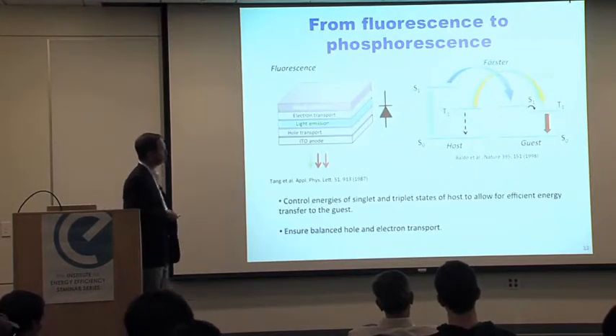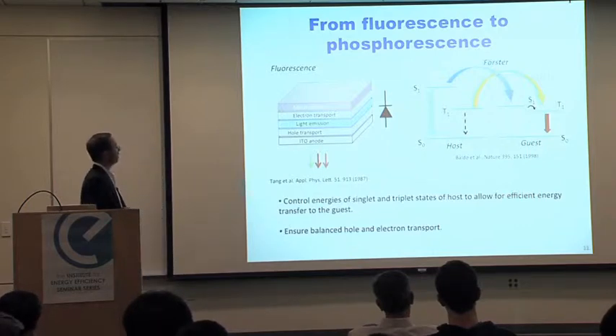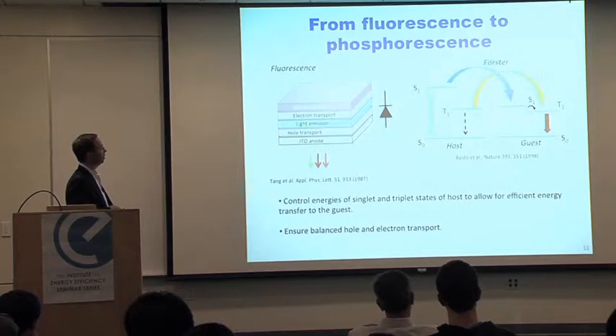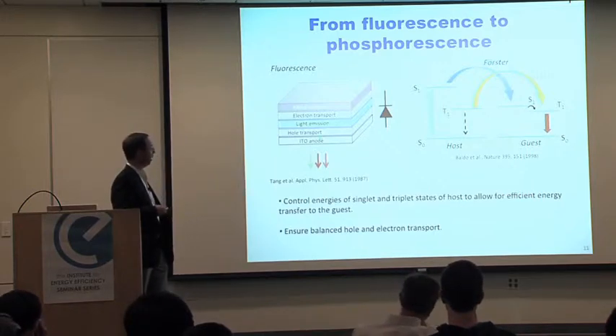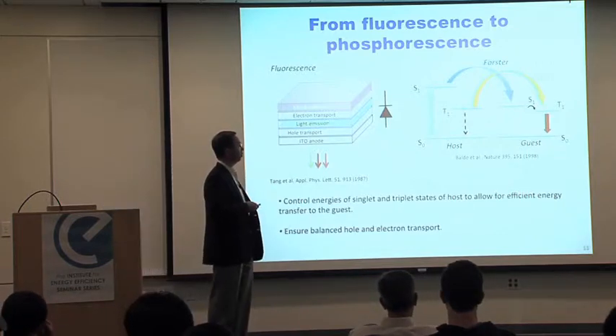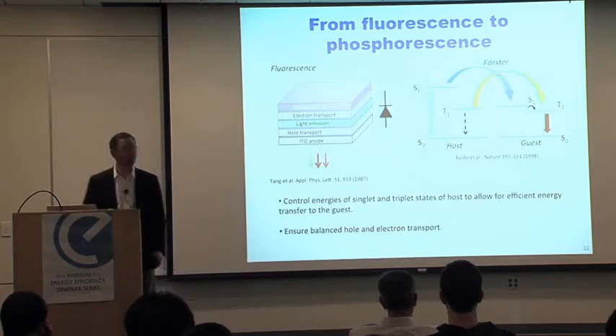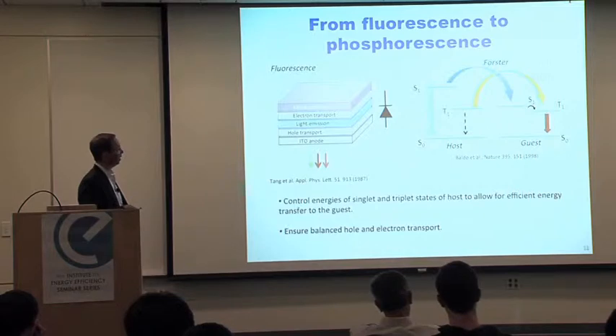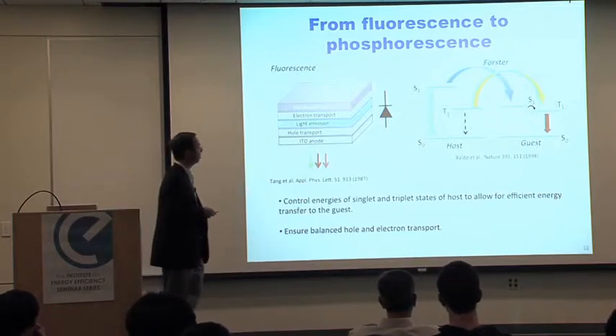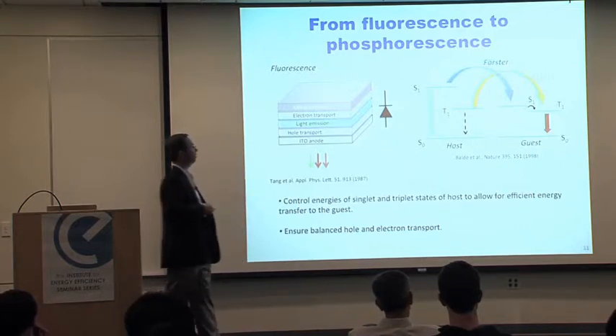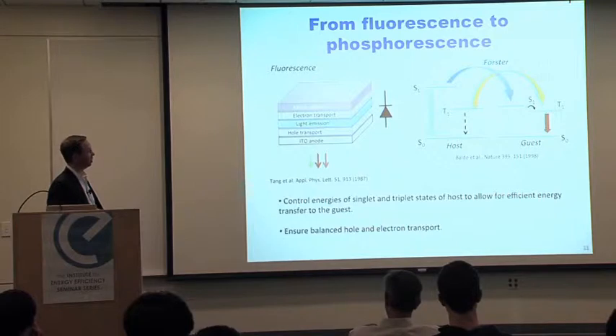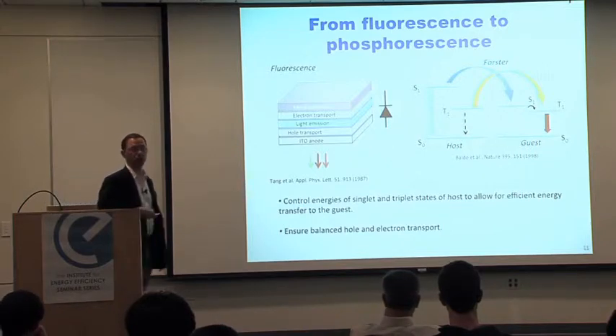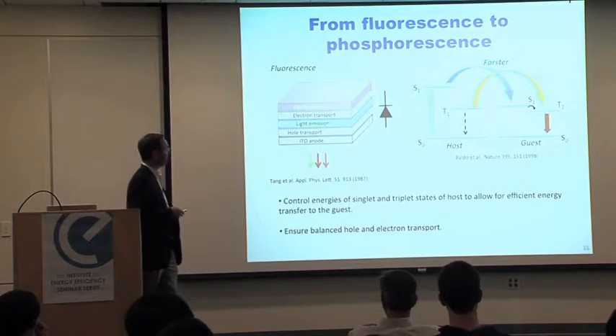Now, the problem in terms of efficiency of these early devices is that it was based on the fluorescence of these light emitters. And so if you look at the electronic states of these organic molecules, and you're creating excited states through the injection of holes and electrons, you can form either singlet states or triplet states, okay? And in these fluorescent molecules, only emission can take place from the singlet excited state back to the singlet ground state, because the transition here from the triplet state is forbidden, okay? Which kind of limits the overall internal efficiency of these devices to the singlet-triplet branching ratio, which was 25%.